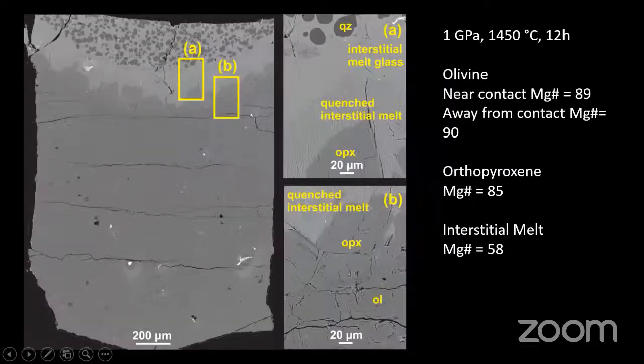At even higher degrees of melting, what we have is mainly melt and quartz. And then in the reaction zone, orthopyroxene is back. We do not find any more clinopyroxene in the reaction zone, just orthopyroxene, and under that we find the olivine layer.